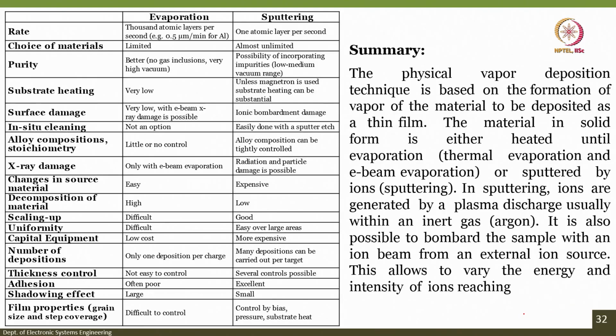So, in a way, if you want to see the last slide and understand how we can compare two different techniques, evaporation and sputtering, and then we will see the summary of it. Okay. So, first is if you want to compare the rate at which the film is deposited or formed. So, thousands of atomic layers per second, 0.5 micron per minute, it is super fast, right, and sputtering is one atomic layer per second. So, the quality is better, this is faster. Second one is choice of material. So, in evaporation we have limited, but in sputtering almost unlimited, we can sputter almost every material.